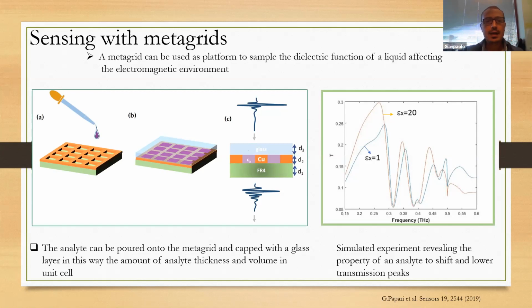I have to say that the analyte in this case is studied just changing its real part. The imaginary part of the analyte is kept to 0 just because this is a beginning work. What we observe when we have realized this kind of structure is that the transmission peaks undergo a shift according to the dielectric constant of the analyte. Therefore, if we can monitor and study the change of the position of these peaks according to the dielectric constant of the analyte, we can make a label-free sensing.